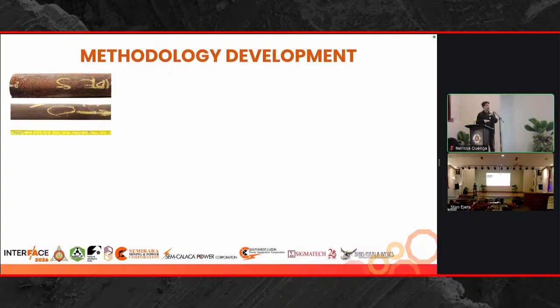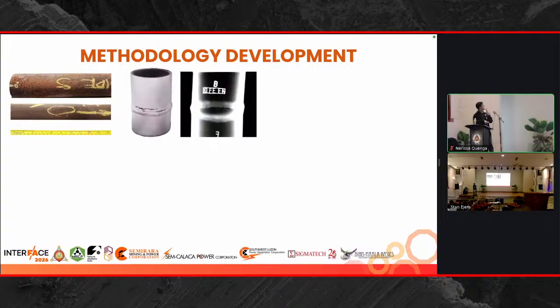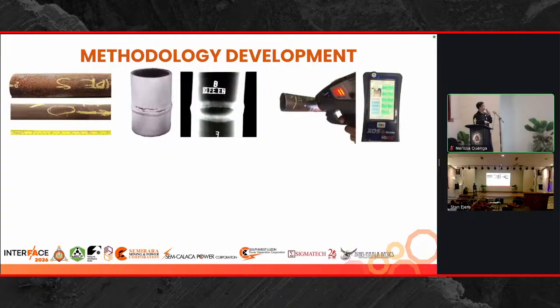So depending on the sample that is delivered to us, then we, of course, conduct more non-destructive tests such as dye-penetrant testing and radiographic testing and elemental analysis so that we can confirm if the specified material grade still adheres with the original one.